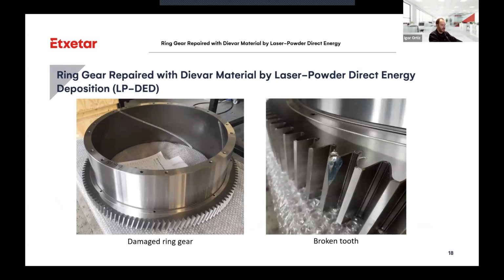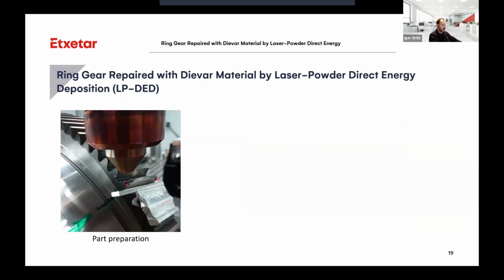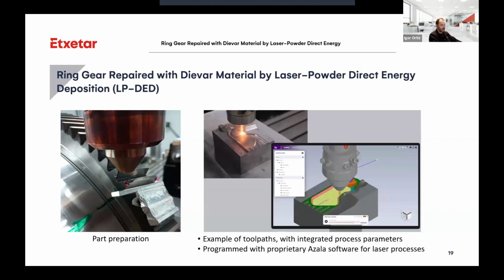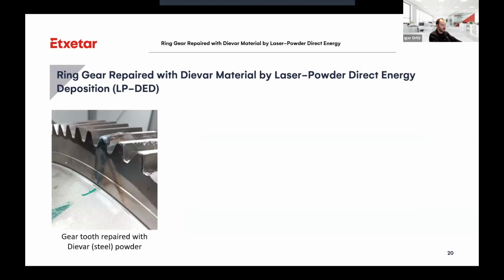So to take the repair process with laser DED, we have previously studied the material behavior with Dievar, and also we have done some preparation, and we have been talking with Azala about whether this root area can be not affected by the heat affected zone of the heat that the laser inputs. So we have done some tests with the toolpaths, also developing new process parameters with Dievar material. We have programmed the process parameters, or we have uploaded the process parameters in our software, and we have developed the repair process of the gear tooth with the toolpaths that previously were programmed.